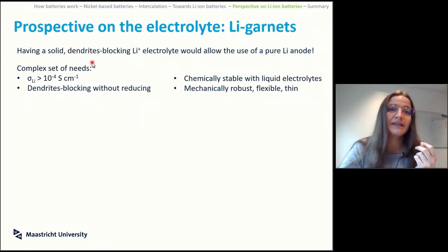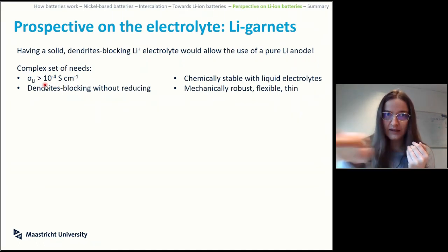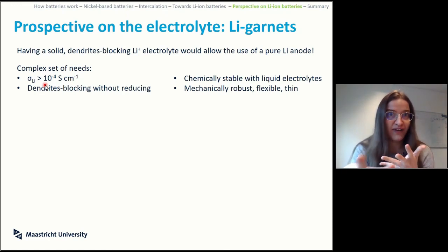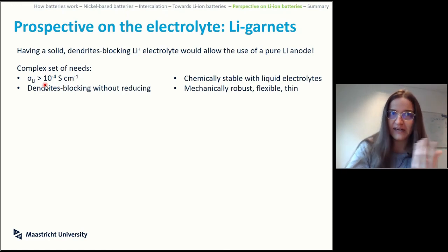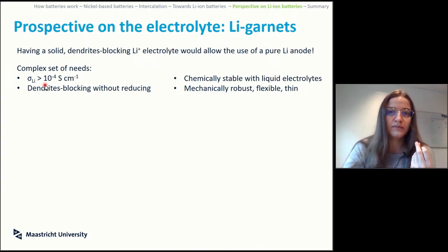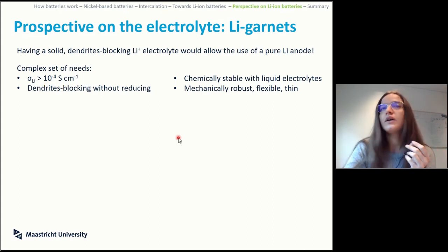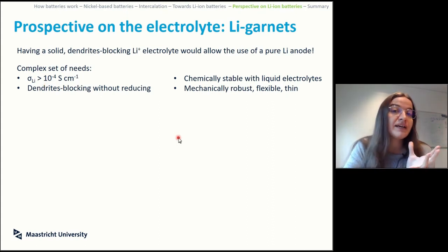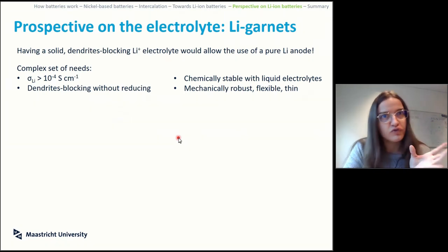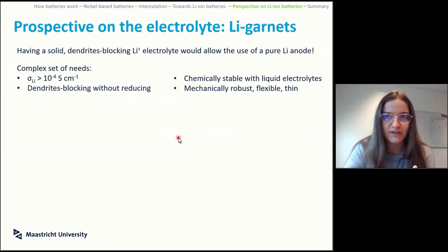But the needs for this thing are very complex, because you need a high conductivity, so you need to be able to get lithium through a solid structure fast without any interface in between that is not a solid. Everything is solid, right? It needs to be chemically stable, mechanically robust, but possibly flexible, because you need to arrange your structure, and you need to have it electrochemically stable as well, so it must not reduce, oxidize, not conduct electricity and stuff like that.